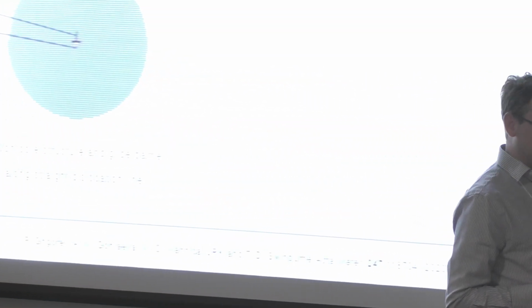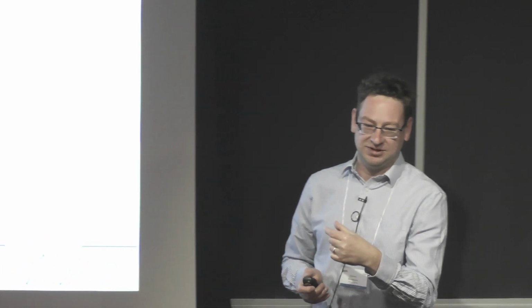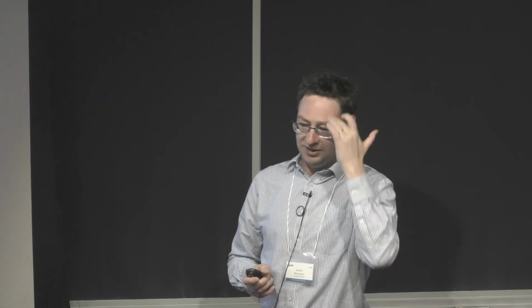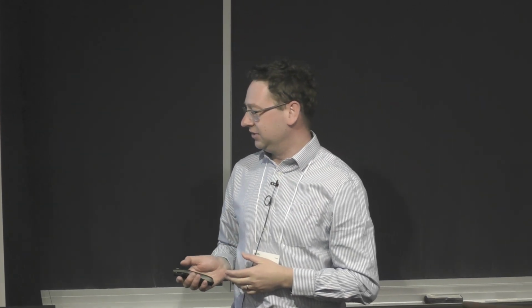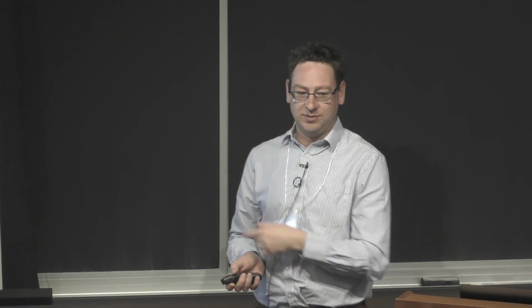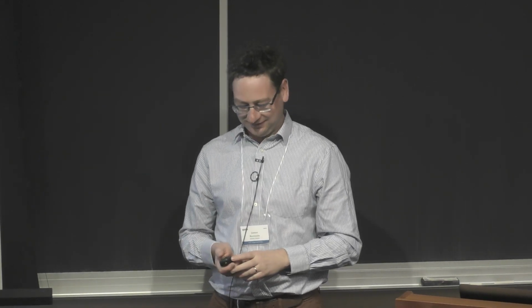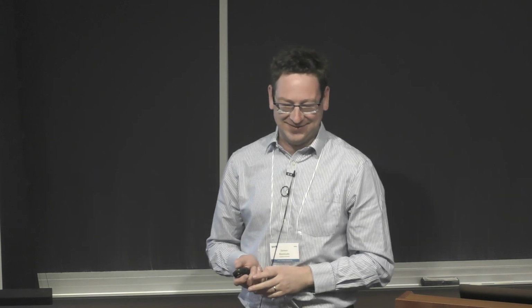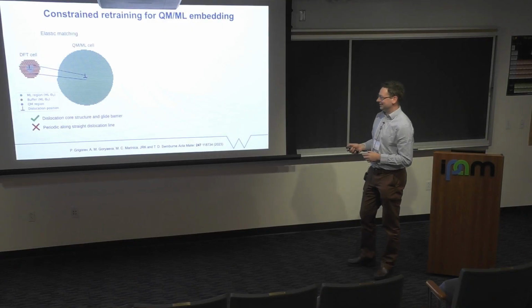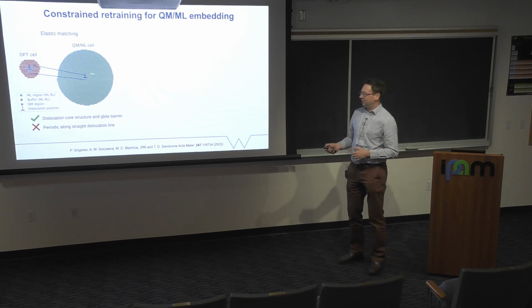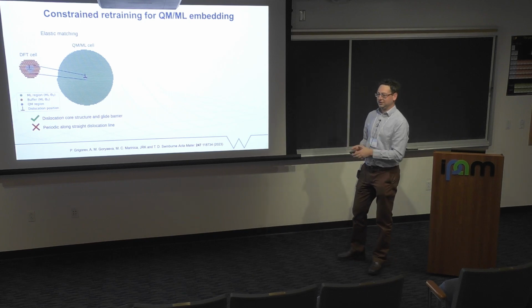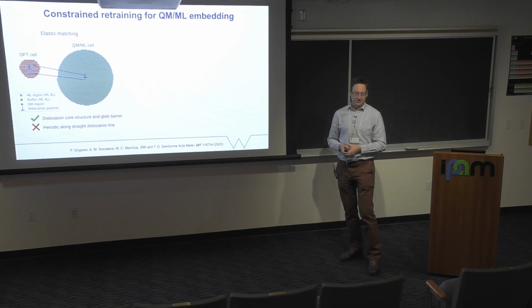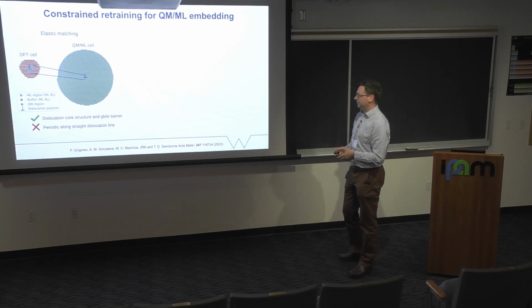Okay, so the simulations I showed you so far were all quasi two-dimensional. The fracture crack front line was quite short, and that was a little bit limiting. So I want to tell you a little bit about some work that's been done with Petr Grigorev and Tom Swinburne. Some of you might have seen a poster about this outside a couple of days ago, so I won't spend too much time on it, but it's a really nice idea because what we do essentially is take the kind of simulations that I've shown you just now for cracks, apply them also to dislocations. This is a screw dislocation in tungsten, so relevant for the plasma-facing applications that I mentioned.